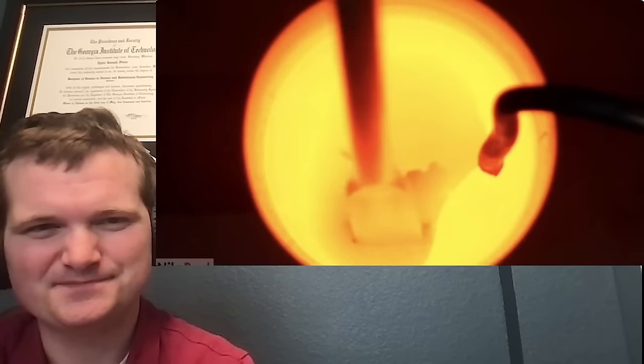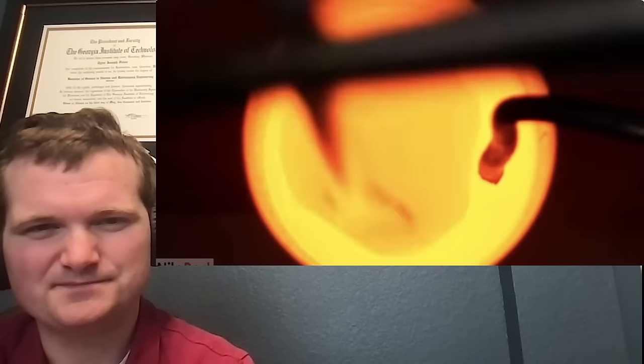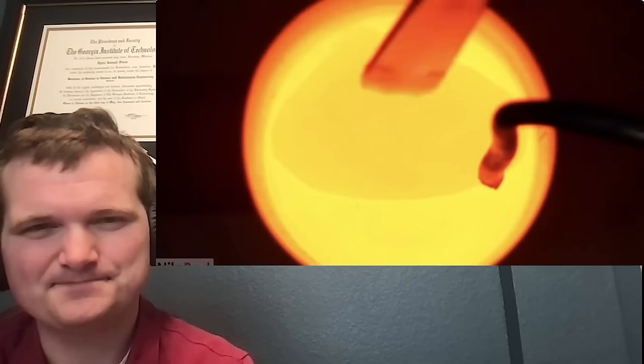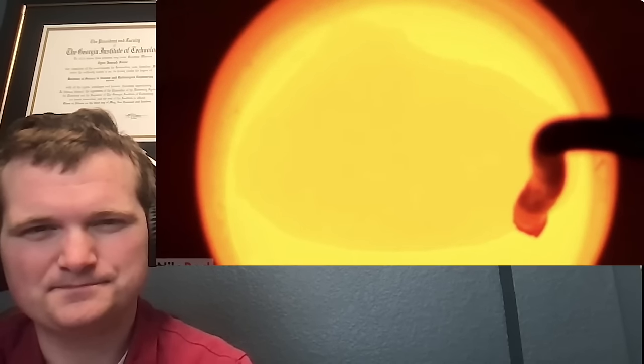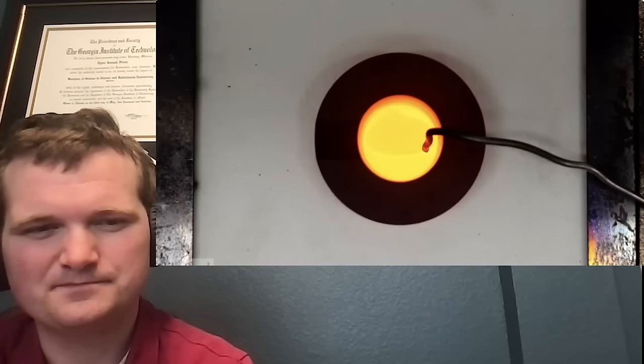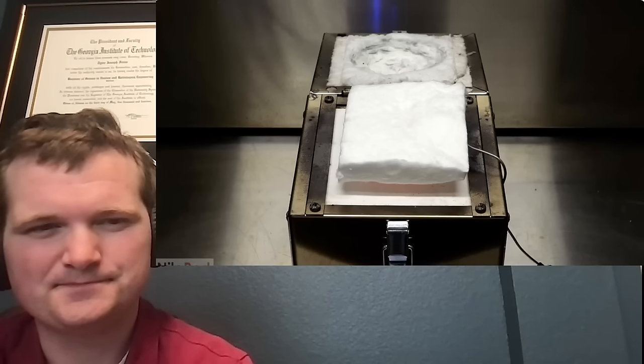What I was excited about was that it looked like there were barely any oxides, and this meant that the argon was doing a decent job. This was also really impressive considering that the aluminum was red hot and that it was way more reactive than normal liquid aluminum. But anyway, what I had now was some nice and relatively oxide-free purple gold, and what I had to do next was try and pour it. In theory, it probably would have been a good idea to protect it from air while I did that as well.